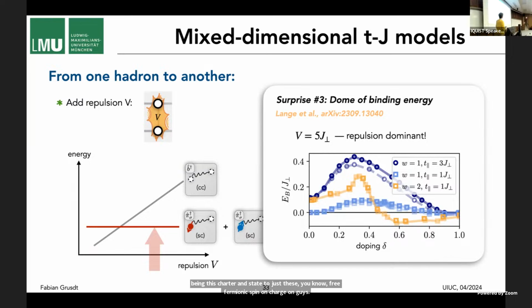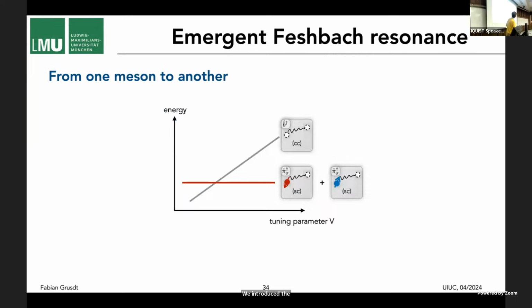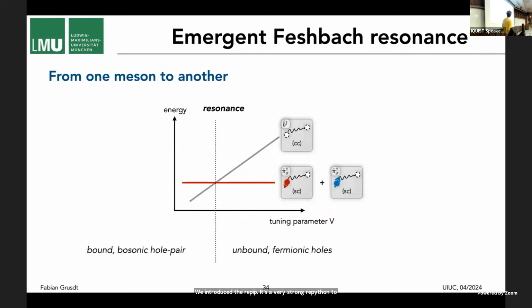So we did this in the simple toy model here and looked at the binding energies that we get at a repulsion which is 5 times J perp. That's definitely enough to break up these charge-on states. But nevertheless, we find, as a function of doping, binding energies that are sizable and positive. That means these holes still bind together. And this begs the question, why do they bind? We introduced a very strong repulsion to break up these charge-on states, so where does this come from? Let's look at this again and ask, if they bind, what type of physics do we get?